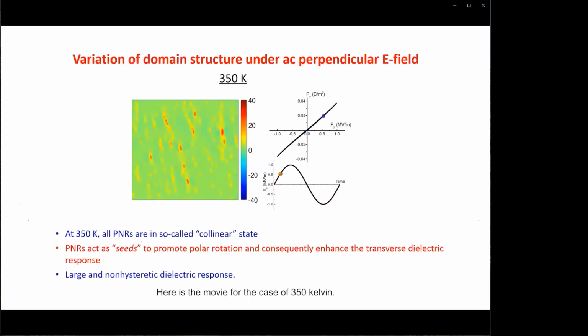Here is the movie for the case of 350 Kelvin. As you can see here, polynanoregions act as seeds to promote the polarization rotation process. Because there isn't any contribution from PNR switching, we can see that the PE loop here is non-hysteretic.